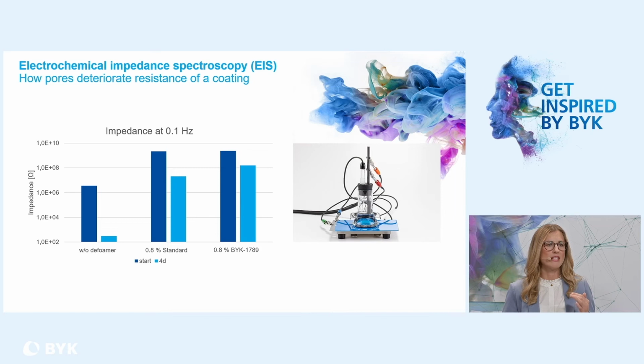So the sample without any defoamer has lots of surface defects, as it is quite easy for the sodium chloride solution to penetrate into the pores and voids of the coating. Therefore, both the initial resistance and the resistance after 4 days is quite low, which indicates worse anti-corrosion properties. By using a defoamer, the air entrapments are released, and therefore the water uptake is minimized. The electrical resistance is for that reason much higher, even after 4 days of exposure.